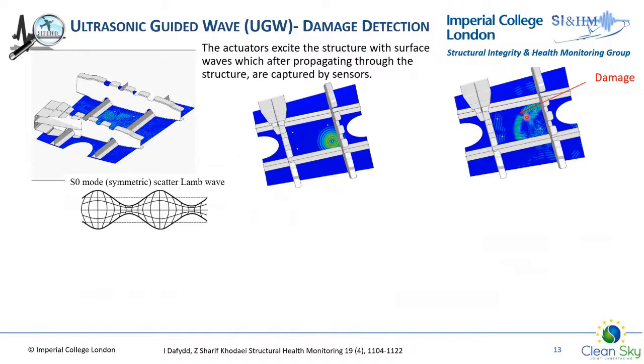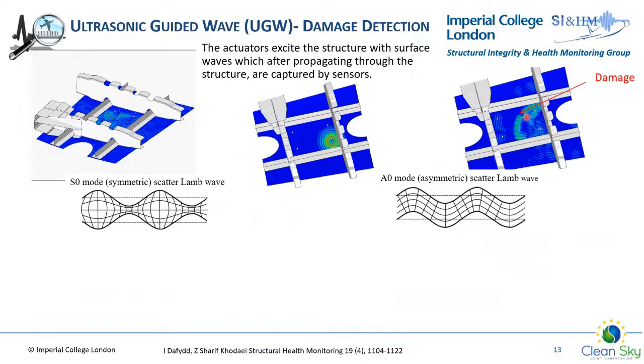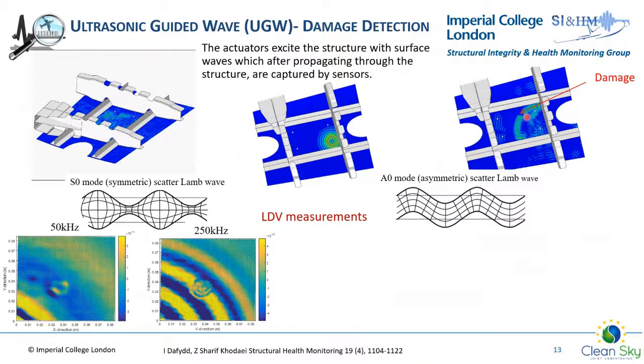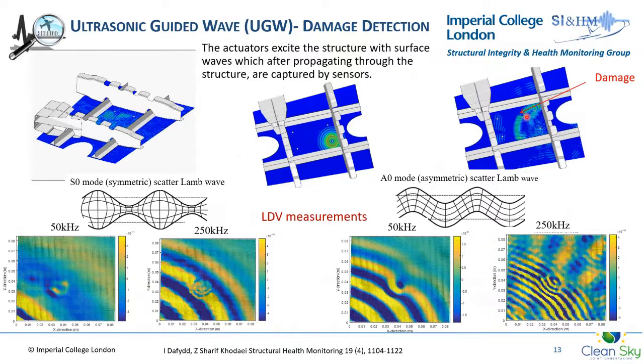designing an SHM methodology. First of all, they are multimodal, so there are different modes, symmetric and anti-symmetric modes. These are with respect to the mid surface of the plate, and they have different properties: how they propagate through the structure, different velocities, and so on. I'm not going to go through the details of it, but here is an example of a full wave field measurement with a laser Doppler vibrometer, where you can see that excitation at different frequencies, 50 kilohertz or 250 kilohertz, excites different modes, as a dominant symmetric mode or a dominant anti-symmetric mode. You see that they have different wavelengths.